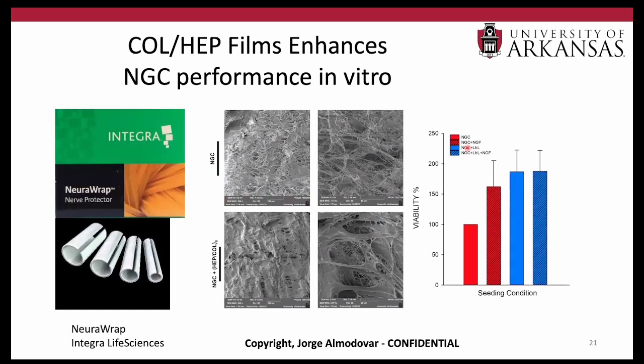All right, so to wrap up this project, we wanted to see if we could do these coatings on an actual nerve guide conduit. And for that, we used Integra LifeSciences' NeuraWrap that is shown here. I'm just going to show you some quick SEM images before and after doing the coatings, just to show that the morphology of the scaffold is not changed. Again, keep in mind that these are nanometer thin coatings, so we don't expect the coatings to affect the bulk properties of the scaffold.